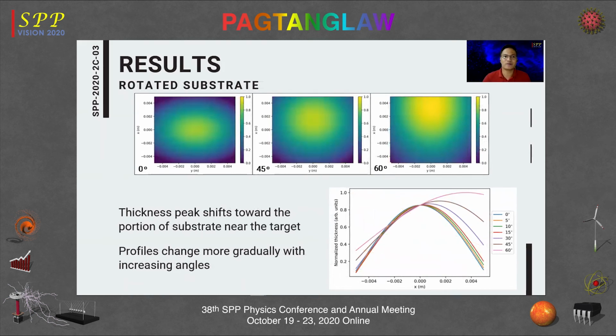On the other hand, for the rotated substrate, the thickness peak shifts towards the portion of the substrate that is near the target. As you can see, as you rotate the substrate, a portion of the substrate is nearer to the plasma plume. So therefore, the thickness profile here has a maximum that is higher than the previous angle configurations.